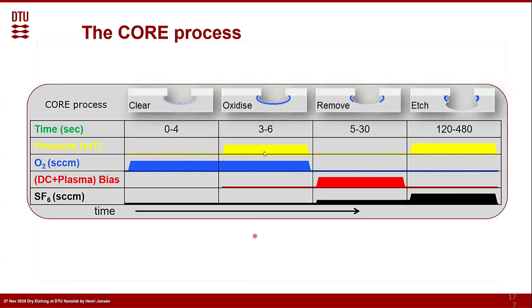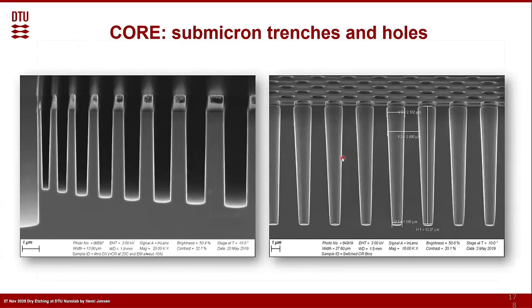But if you do directly the oxidation, it might be that they are already oxidized inside the plasma reactor while they are still close to the wafer, and they might create silicon oxide particles, and that creates what we call black silicon, and I will come back to that later. It's not always needed, but the steps are exactly the same as the Bosch process.